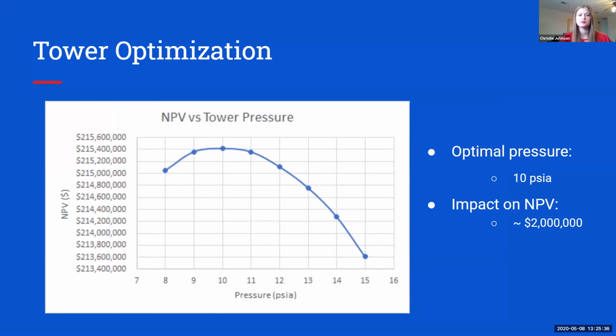Another thing that we optimized with our towers was the pressure. Due to time constraints, we weren't able to optimize the pressure of each tower individually, which would be another step in our process as we continue to move on with this. But we did optimize the pressure of the system overall, and found that our towers operated best at a vacuum of 10 psia, and this helped impact our NPV by around another $2 million.